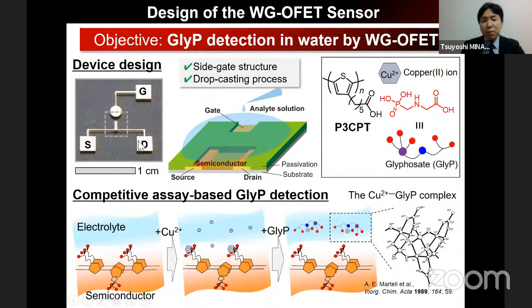So here is the design of the water gate transistor for glyphosate detection. A carboxylate-attached polythiophene unit can make a copper ion complex, and such a complex can detect glyphosate. This is the mechanism: first the copper forms a complex with the carboxylate, while glyphosate can strongly coordinate with the copper ion. Thus, the charge state of the copper ion can change on the surface of the semiconductor layer. I thought we could see such changes based on the equilibrium.